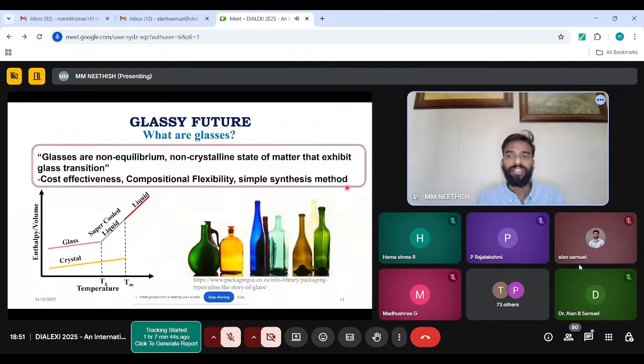And moreover, it is simple synthesis. The normal glass synthesis, as I was saying before, is supercooling. You bring down the temperature of the melt to room temperature very fast. So this synthesis method is very, very easy. And something I forgot to mention here is the recyclability. Glasses are 100% recyclable. So if you create a glass, you break it, or you use it and you want to reuse it, you just need to melt it and supercool it at the same conditions. Like, what were the conditions to make the original glass? Do the same again, and you'll get the same glass. So they are 100% recyclable. This is something promising for the future.